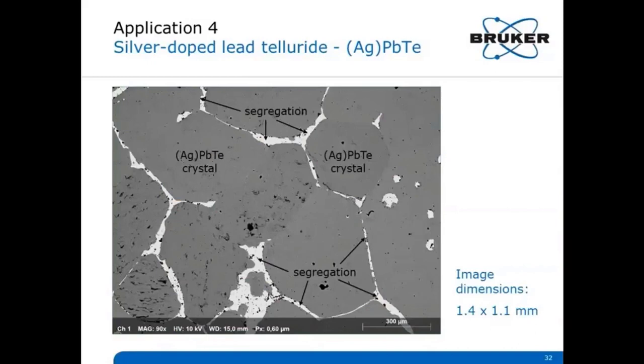Now we have a look on a fourth sample. Another semiconductor sample with an interesting structure is the silver-doped lead telluride. The BSE image nicely shows the hexagonal crystals. So you see here the hexagons nicely as well. So everywhere hexagonal crystals, which are cut perpendicular to their length axis.